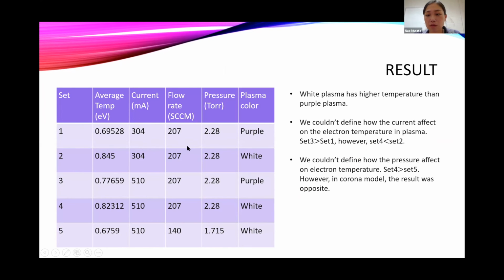Similar to corona model, we see that white plasma has higher temperature than purple plasma. When you look at the set 2 and set 1, set 2 has higher temperature than set 1. Similarly, set 4 has higher temperature than set 3.